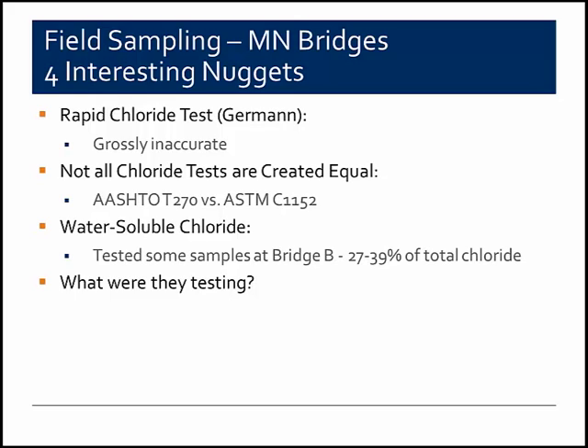So although AASHTO tests were run for the initial bridge that we sampled, they were dropped for the remaining bridges in favor of ASTM C1152. In addition, on one of the bridges that were sampled, Bridge B, because we had a little extra sample, we decided to run a water-soluble chloride content test in addition to the acid-soluble chloride content. And we tested several of the samples that were collected, and what we found was that only 27 to 39% of the total acid-soluble chloride content was water-soluble, which I think was somewhat surprising and certainly lower than the fraction that we expected.